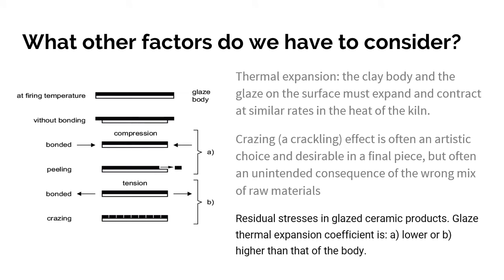So what other factors do we have to consider? We have to consider how hot we're making the kiln. You've probably heard of cone 6, cone 10, cone 05. Those are different temperatures that the kiln is going to reach. So when you're making a glaze, you have to look at the balance between the glass formers, the glass melters, and the glass stabilizers, and make sure that they are going to expand and contract at about the same rate as your clay body. So you really can't just go and dig clay out of your backyard and necessarily make a piece that will end up being functional at the end of the day, only because you don't know exactly what's in that clay and what temperature you need to fire it at to make it stable. So when making a glaze, we also have to consider, is it a mid-fire or a high-fire glaze, and working with that clay body.